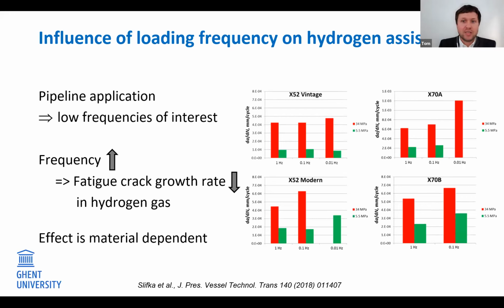As lowering the loading cycle frequency extends the exposure time of the material to the hydrogen gas environment, more atoms of hydrogen are able to absorb in the steel microstructure and can diffuse over longer distances to the crack tip region with each loading cycle. The paper presented here investigated the effect of loading frequency and hydrogen pressure for a vintage and also a modern steel. So a vintage and a modern X52 and 2 modern X70 steels.